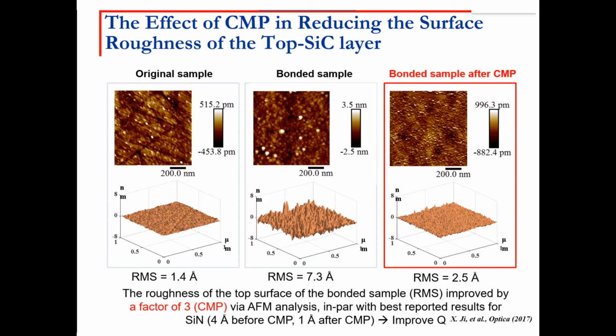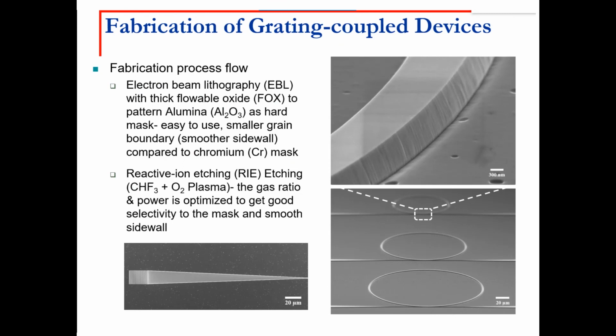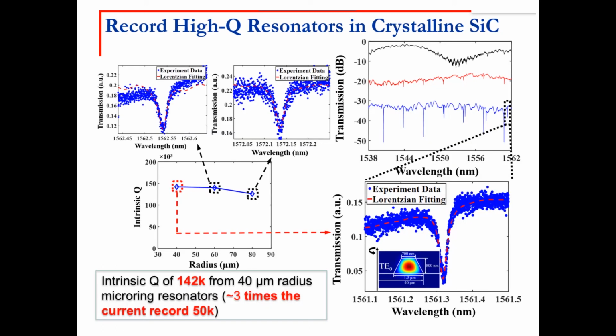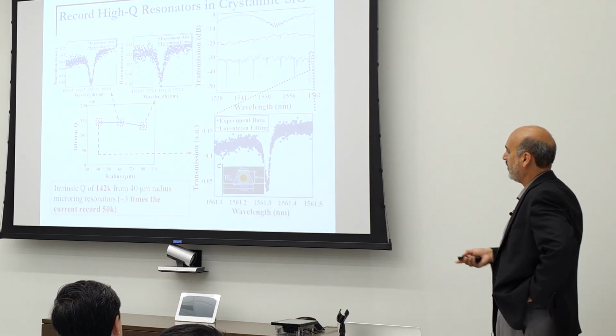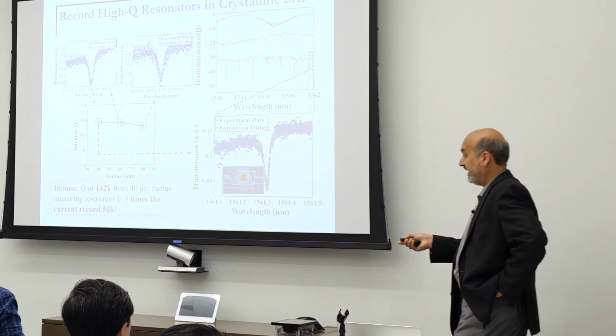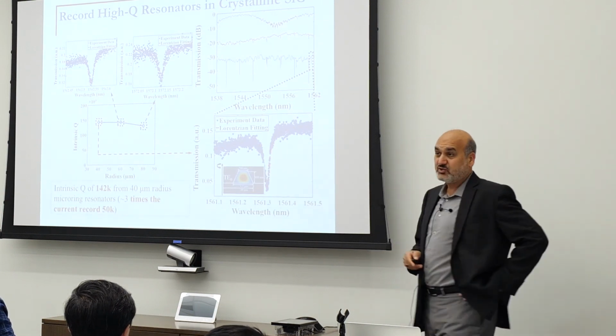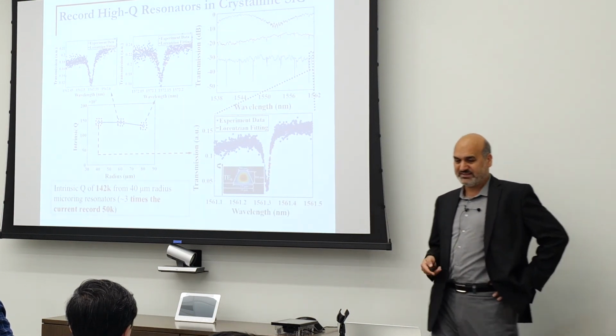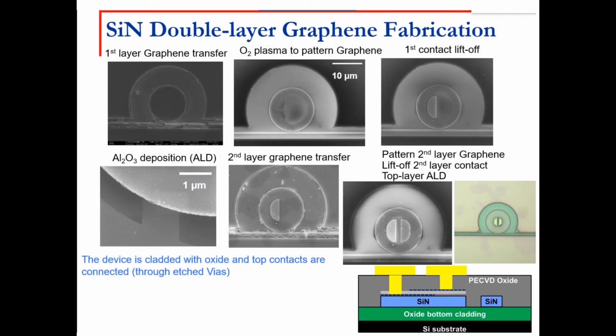Using that, we fabricate the structures in the silicon carbide on oxide, and then we use grating for coupling and so on. And this is the result of the quality factor of these resonators. This is the transmission through that waveguide, and the dip shows the resonance mode. And by focusing on each resonance mode, we can get quality factors. And this is the highest reported to date. So we can bring quantum features to the chip if we want, thanks to silicon carbide.